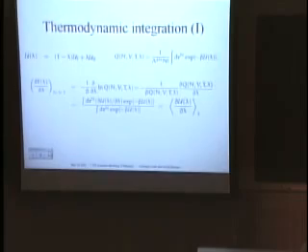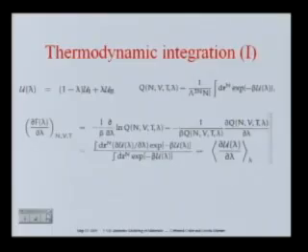That is a technique that has been discussed in some of the previous lectures by Professor Sider, so I've just put up a reminder here. And the nomenclature is that we are using a Hamiltonian or an energy model that depends on a parameter lambda. The parameter lambda is something that brings us from the solid to the liquid, because ultimately what we want to figure out is the difference in Gibbs free energy between the liquid and the solid, or maybe between two solids, between one reference phase of the solid and another reference phase of the solid.